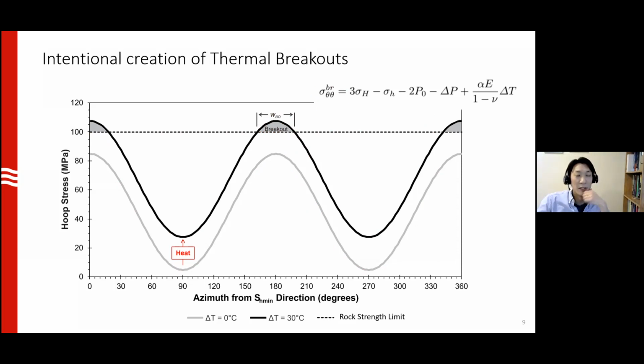The equation on the top right is the Kirsch solution, which applies just for the maximum value of the hoop stress. But as you can see, you can relate the amount of hoop stress you get with the amount of temperature, as long as you have the proper thermoelastic properties, elastic moduli and Poisson's ratio. So this gives us an idea that if we can measure the delta T that is required to create this breakout, we can also back out what the stress magnitudes were that created this sinusoidal curve.